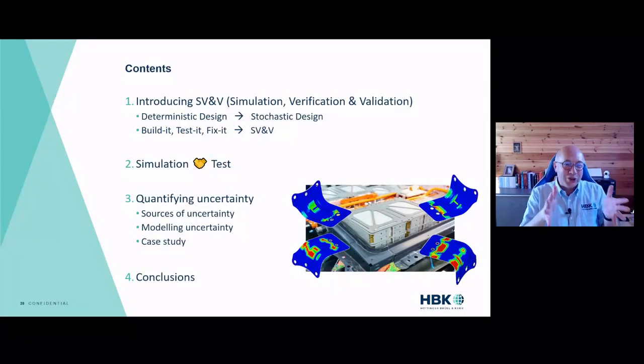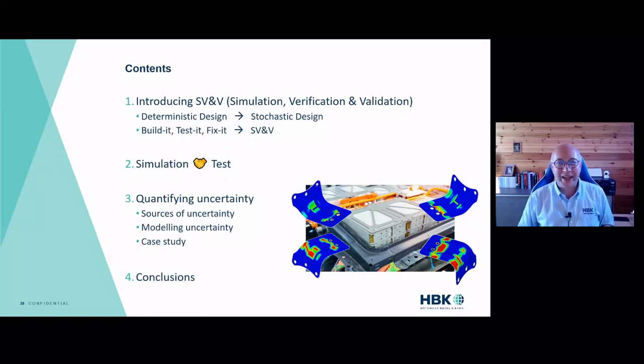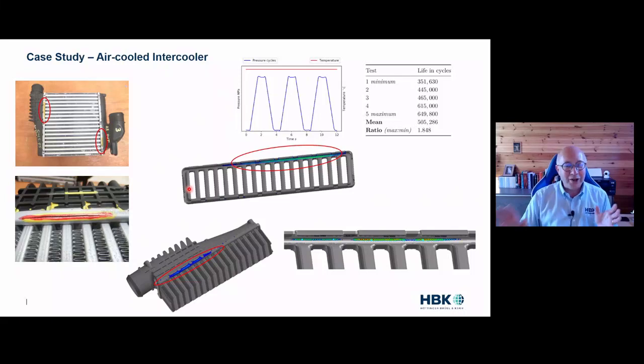So we've looked at the sources of uncertainty, how we model them mathematically. Let's finish off with a case study. So in this particular case, we're looking at the fatigue of an air-cooled intercooler. And we can see highlighted here is where the failures are occurring. And in this test, it's actually performed at a high temperature, so the intercooler is kept at a high temperature, and then we provide pressure cycles.